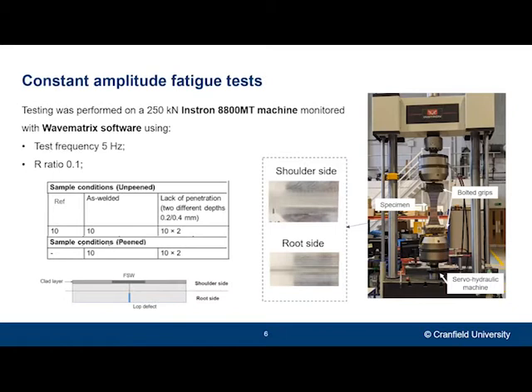And these are what we call lack of penetration defects, which form when there is an incomplete bonding of the 2 plates. So if you think that we're trying to join these 2 plates of aluminium, the tool will be on the top rotating, and that side is called the shoulder side, and the opposite side is the root side, which you can see in these pictures. So the lack of penetration defect will be on the root side if there's incomplete bonding of these 2 plates.